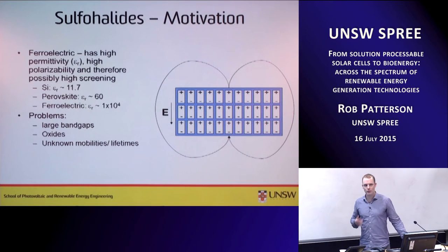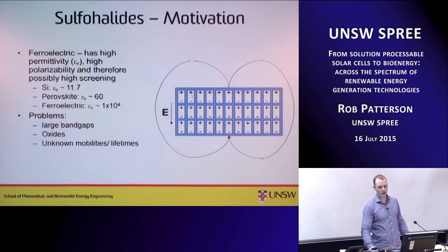These materials have the potential to be ferroelectric. What does that mean? That means that the materials have a high polarizability. We have little dipoles in the material, which are forced to be aligned with each other. And so there are domain walls as well, just like a magnet. We can have some of these guys out of alignment, but they're either aligned or anti-aligned, depending on whether you're ferroelectric or anti-ferroelectric. And this high polarizability or high permittivity is a potential way to increase screening in the material. And the screening is what I want to talk about today.